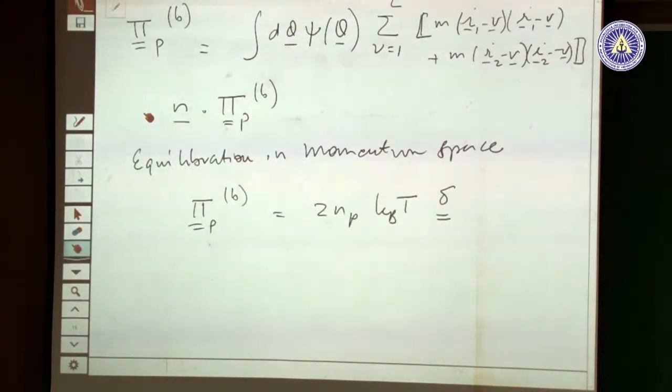So, this will not contribute, because it is a diagonal component. Secondly, you always measure differences in normal stresses. That is why you have the first normal stress difference coefficient and the second normal stress difference coefficient, because there is no way you can separate, when you have a normal force on a surface, what is the pressure contribution and what is because of the deviatoric part. All you will measure is a normal force. So, you have to take the difference between two normal forces to get rid of that pressure part, and that is why isotropic contributions are never taken into account. So, we know this now.